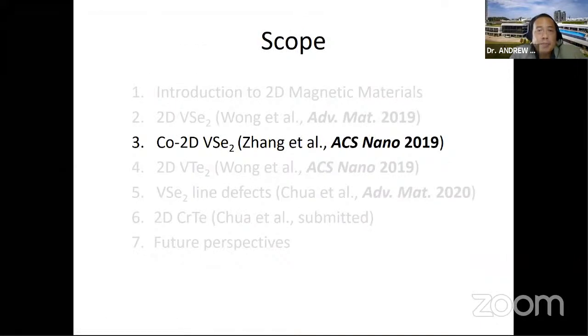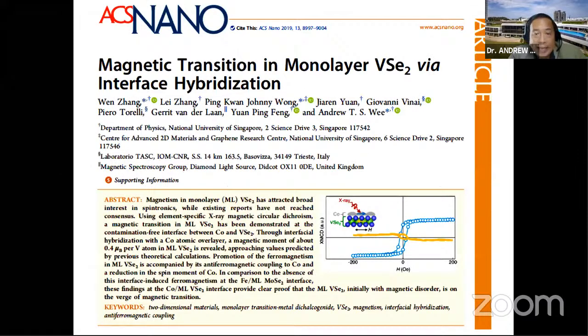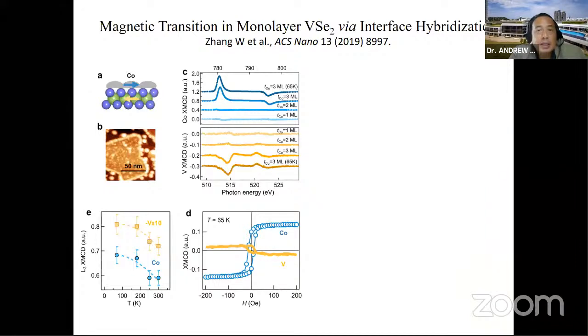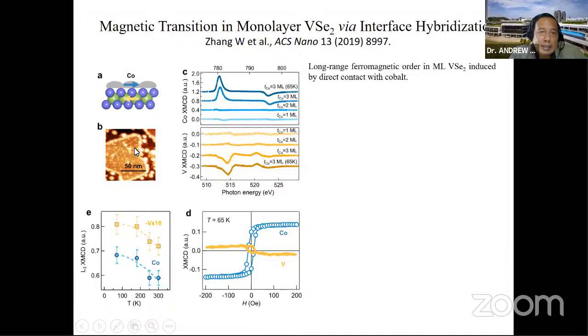And we confirmed that when we put some magnetic element like cobalt on this vanadium diselenide, then we see an XMCD signal from vanadium as well as the cobalt. And the interesting thing is that the dichroism is in opposite directions. So these are the results. This is the XMCD result. This is the STM. You can see the cobalt is clustered. It's not a very uniform film, but nevertheless, it's about 3 monolayers.